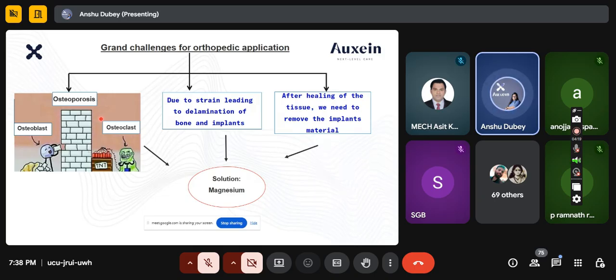If there is a mismatch in the elastic modulus, it will lead to a stress concentration area at the implant which has been attached to the bone, and that will lead to stress shielding. Due to that strain, it will also delaminate the implant from the bone. So these were the major issues with the conventional metallic implants. Further, after healing of the bone, what is the point of having an implant inside the body? So we should come up with a solution: use a material inside the body which will degrade with the healing of the bone.